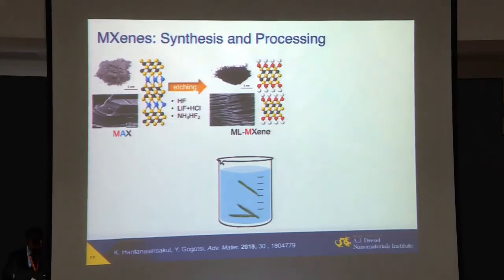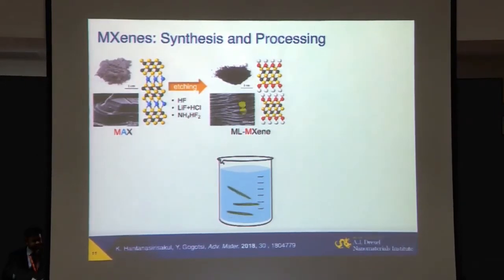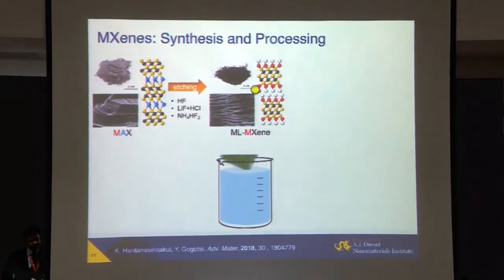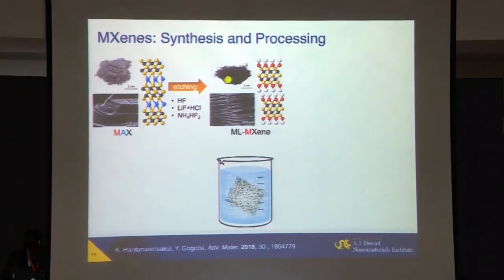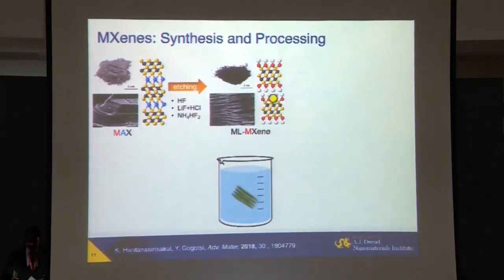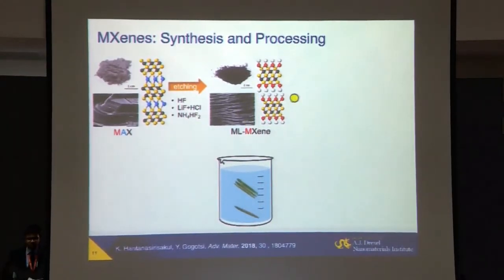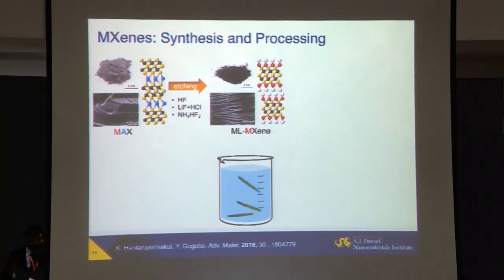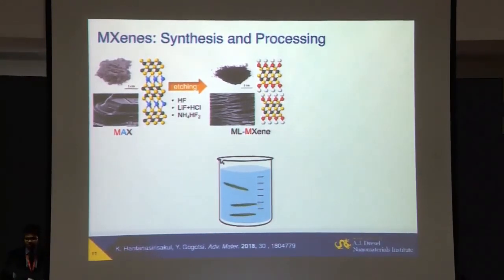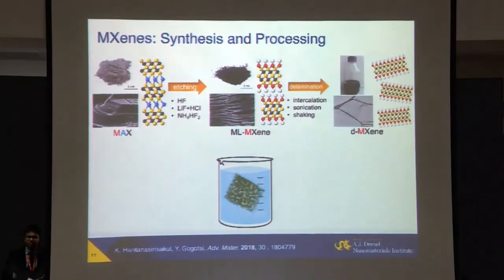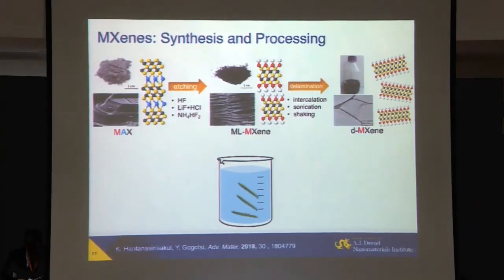What we have now, we have MXene layers, which are still bonded to each other. You see, this picture looks like a thermally exfoliated graphite or vermiculite clay. But now they're bonded by weak hydrogen bonds because there are OH or oxygen or fluorine groups on the surface. So we can disperse them just the same way we would disperse graphene oxide, clay, or other materials, because now there is a weak bonding.